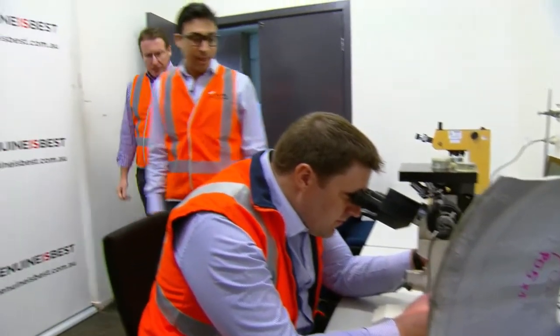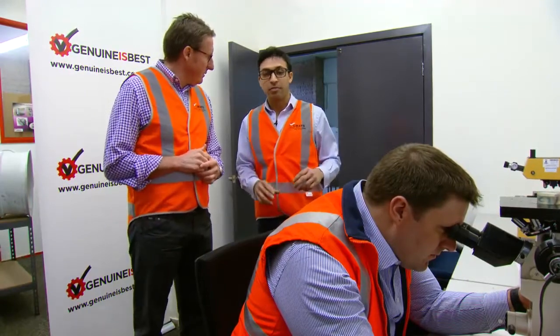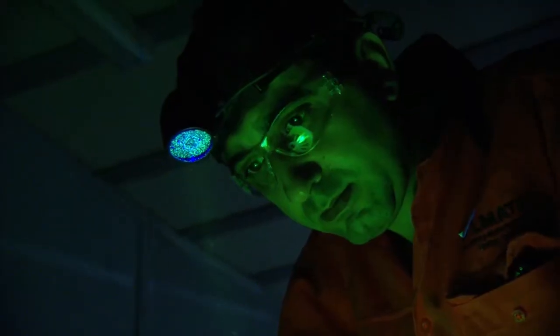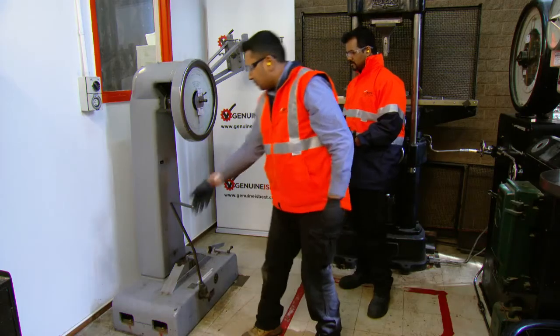So Yashwin, what's the process? So you take the shiny clear coating off those wheels — the counterfeit and original wheel — and put them through a series of metallurgical tests like penetrant testing, radiography, and chemical and mechanical tests like tensile, hardness, and impact testing.